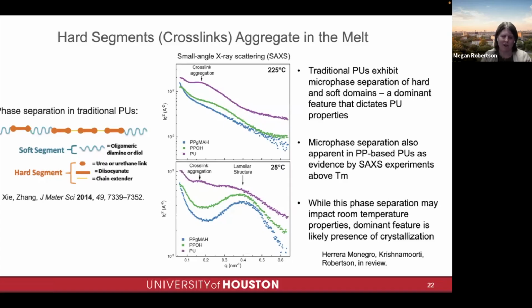So we can consider our cross-links, which are the diisocyanate segments coming from the diisocyanate. They're coming together. They don't really want to be in the presence of the polypropylene. The polypropylene is kind of excluding those isocyanates as well. When it crystallizes, we envision there's mostly polypropylene in the crystalline areas, and in the amorphous regions are these aggregated crosslinks.